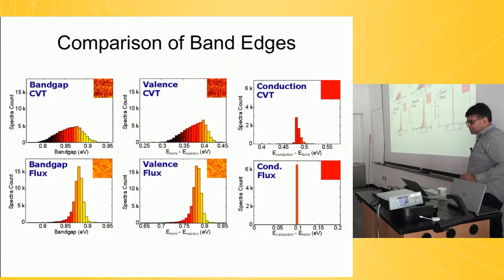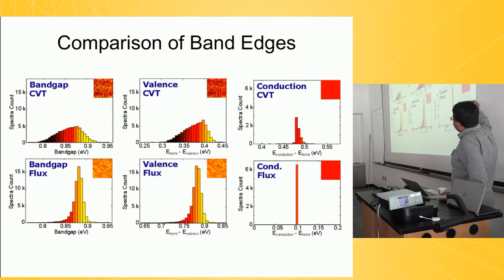We can go a little further and ask, where is this disorder mostly located? So here I'm presenting histograms. These are of the overall band gap. This is the edge of the valence band relative to the Fermi level. This is the edge of the conduction band relative to the Fermi level. And this is for the CVT crystal on the top and for the flux crystal on the bottom. What you see is that most of the disorder in the band gap actually comes from the valence band edge.